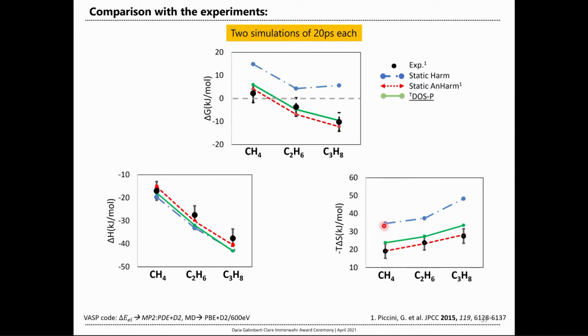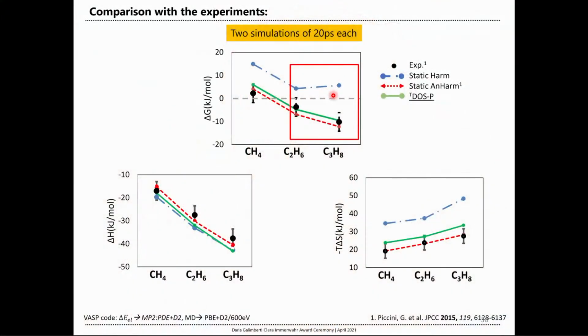We have increased a lot the quality of our prediction of the entropy, and so we have the correct free energy. And I want to underline that to compute this line, we only used 2 molecular dynamics simulations of 20 picoseconds each. And here, most importantly, you can see now that while the propane with the harmonic approximation was predicted to be positive in free energy of adsorption, now we have the correct free energy of adsorption that is negative, and not far from the experimental value.